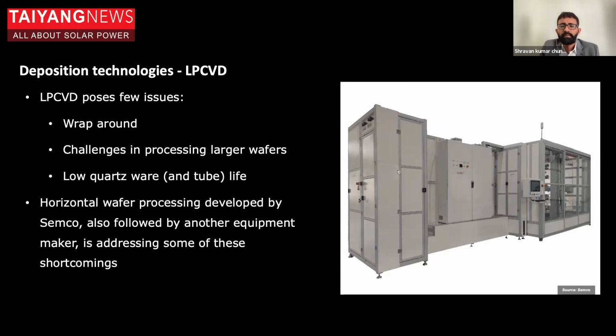And there is another big problem with these LPCVD reactors, which is the cracking of the quartz tubes, not just the quartz tubes, even the quartz ware, because there is a huge variation between the thermal expansion coefficient of polysilicon and quartz. And since the mechanism of LPCVD is that it deposits everywhere.